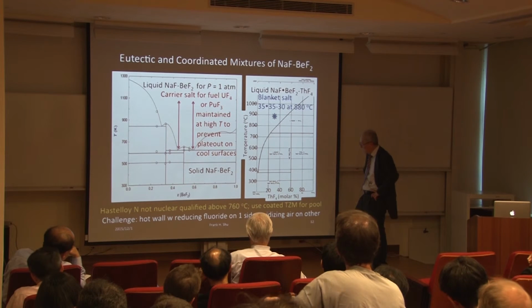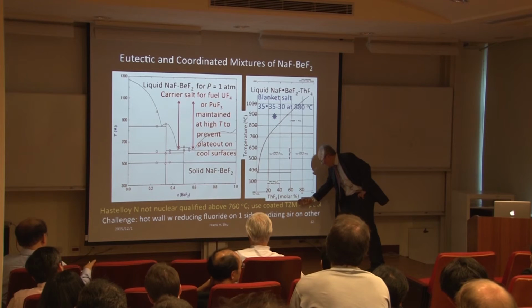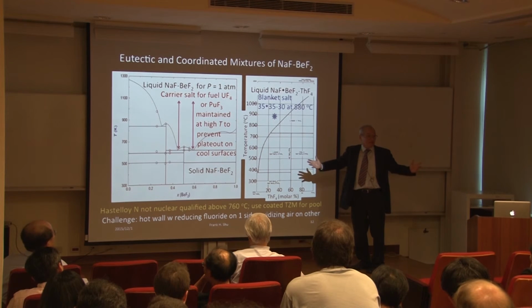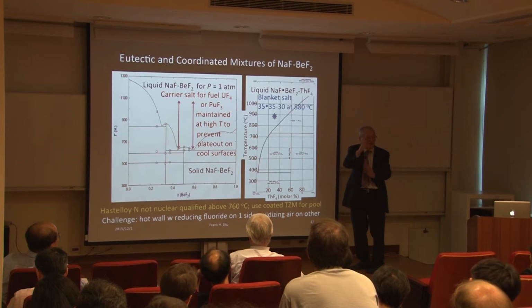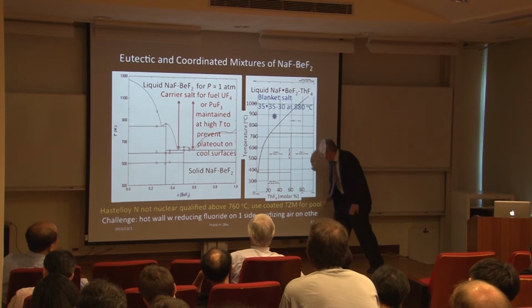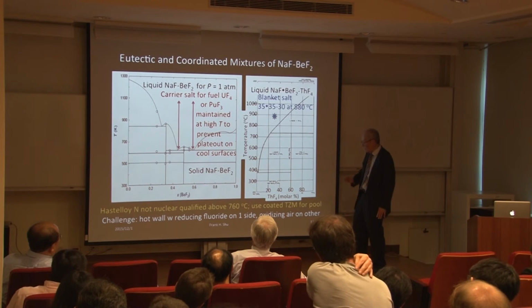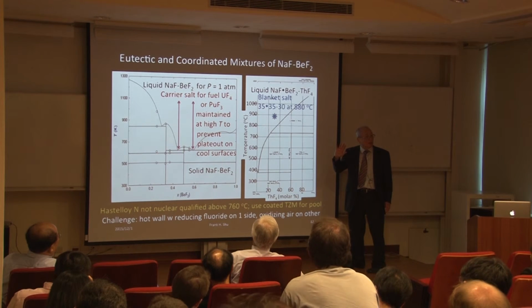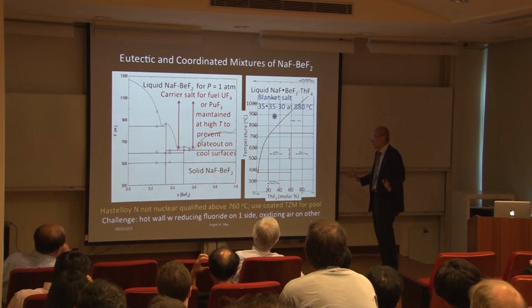So what do we do? Well, I think, but we haven't done this yet, I'm hoping Funtai can do this. I think we can coat it on the inside with molybdenum. Since it's 100% molybdenum, it almost has the same coefficient of expansion as the 99% alloy. So you don't have to worry about it coming off because the temperature changes. On this side, you've got to protect it against oxygen. And the two things that can protect alloys against oxygen are either chromium or aluminum. Aluminum has a terrible coefficient of thermal expansion, so probably not usable. But chromium has almost exactly the same coefficient of thermal expansion. So I'm hoping we can get somebody to make us this and test out the corrosion properties. Anyway, that's a hope. All right?